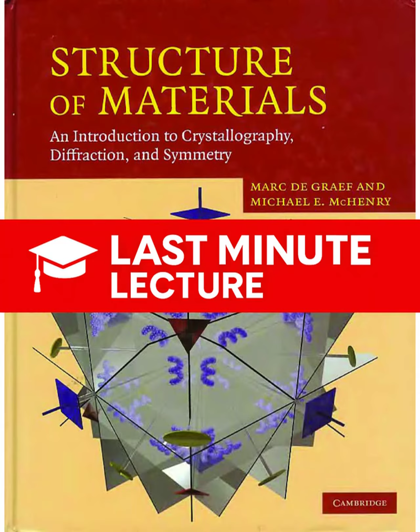The metric tensor is a matrix, a 3x3 matrix, built from the dot products of the basis vectors. The source defines two critical versions. The direct and the reciprocal. Right. The direct metric tensor, G_jk, contains the dot products of the direct basis vectors with each other. This matrix completely defines the geometry of the direct lattice. And the reciprocal metric tensor, G*_ik, does the same for the reciprocal basis vectors. And the truly crucial insight here is the relationship between the two. They are mathematical inverses of each other. The reciprocal metric tensor is the inverse of the direct metric tensor. And that inverse relationship is the bridge we were looking for.